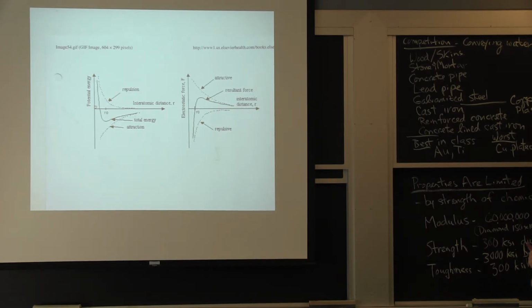You've probably heard about Young's modulus, okay? Young's modulus is related to the curvature of the energy. The second derivative of energy is the modulus of the material. So if I take something that has a very strong bond like tungsten, or a carbon-carbon bond in diamond, which is one of the strongest bonds. The strongest bond, I was once corrected by a chemist, is a silicon-oxygen bond like in silicone polymers, okay? Slightly stronger, but all around 3 electron volts per atom, okay? So in any case, it's the curvature of the energy curve, the slope of the derivative of the energy curve. So this second derivative is the modulus of the material.